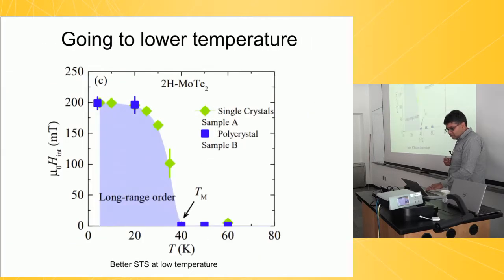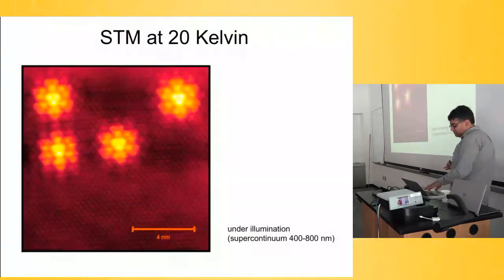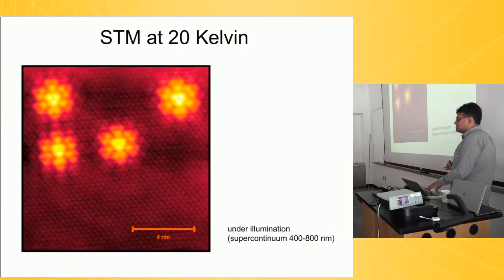Good. Now, more recently, what we decided to do is we need to really go to low temperature to nail this thing down, because at low temperature, everything becomes nicer, STM is nicer. So we found that the samples were insulating, and there's another story which I won't tell you about, but we found that if you shine lasers at these things they become conducting. The laser does nothing other than make it conducting. Take it from me. And now we measure these same defects, and you see that these defects have these beautiful patterns around them. Quite spectacular.